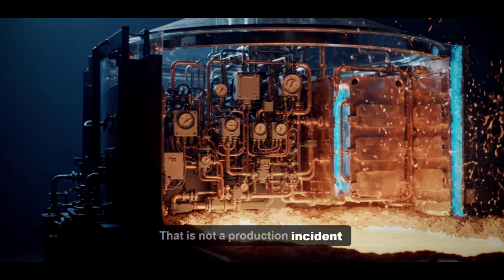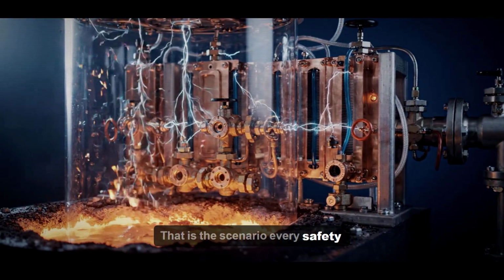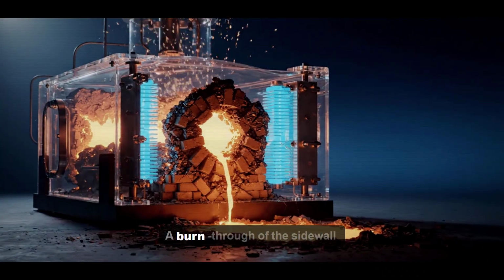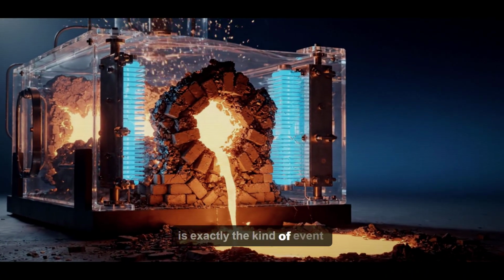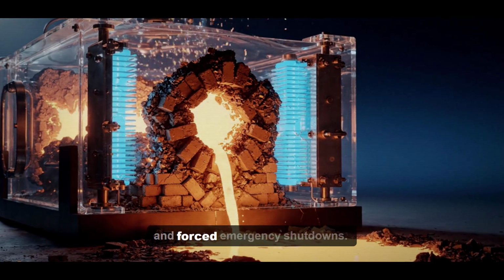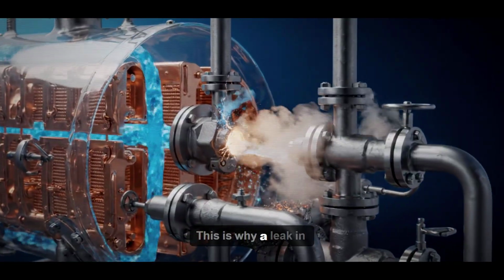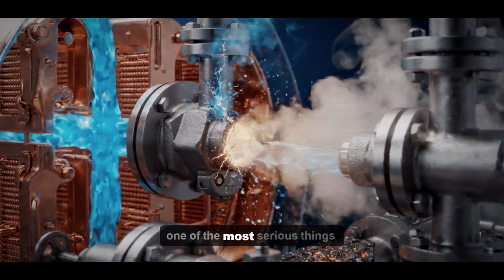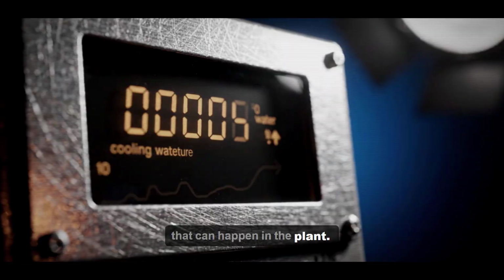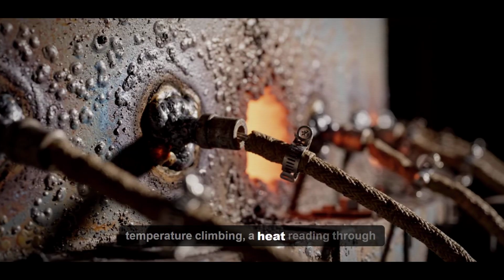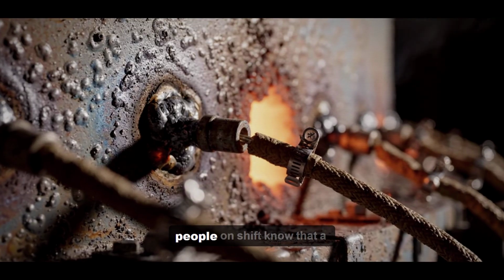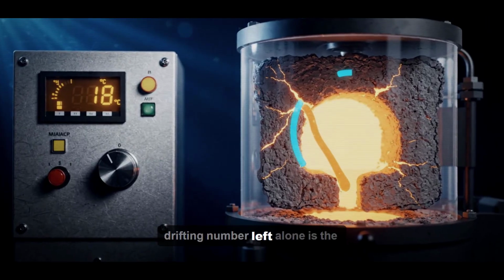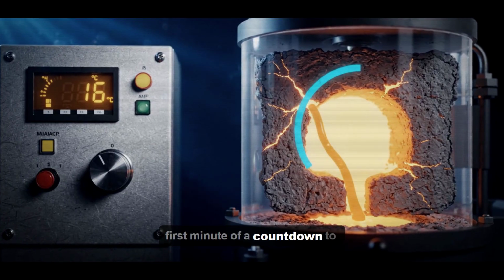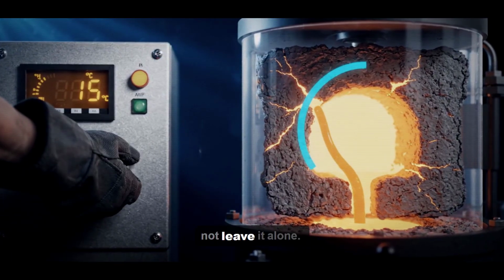That is not a production incident anymore. That is the scenario every safety system in the building exists to prevent. A burn-through of the sidewall is exactly the kind of event that has caused real smelter fires and forced emergency shutdowns. This is why a leak in a cooling circuit is treated as one of the most serious things that can happen in the plant. It does not announce itself as a catastrophe. It starts as a number drifting on a screen, a cooling water temperature climbing, a heat reading through the shell creeping up, and the people on shift know that a drifting number, left alone, is the first minute of a countdown to a molten breakout, so they do not leave it alone.